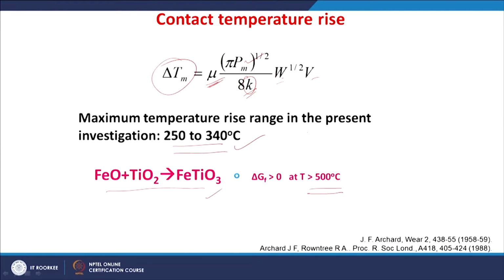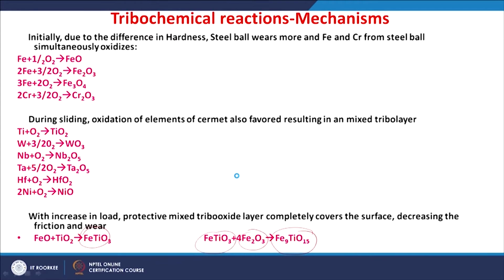So, it is now very clear that the formation of these oxides on the surface will lead to the mixture of this iron oxide and titanium oxide and then lead to iron titanate. So, this iron titanate is thick and also viscous in nature, and it actually facilitates the sliding. So, the friction is reduced because of the coverage of this layer. So, the material removal is also reduced.